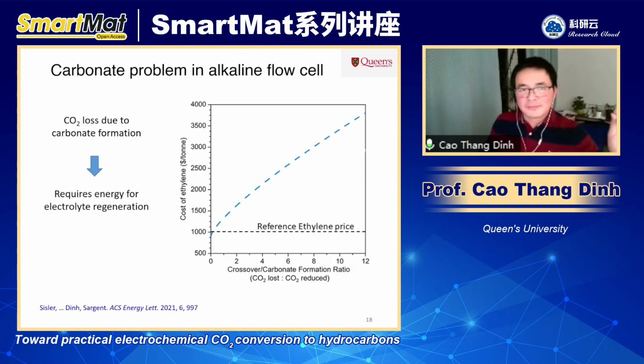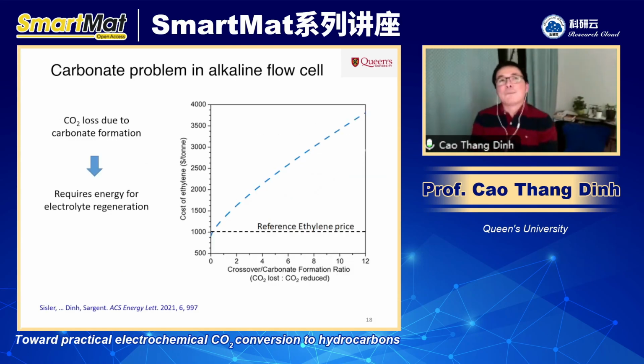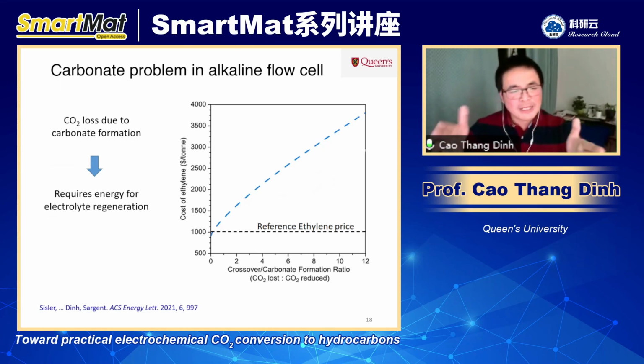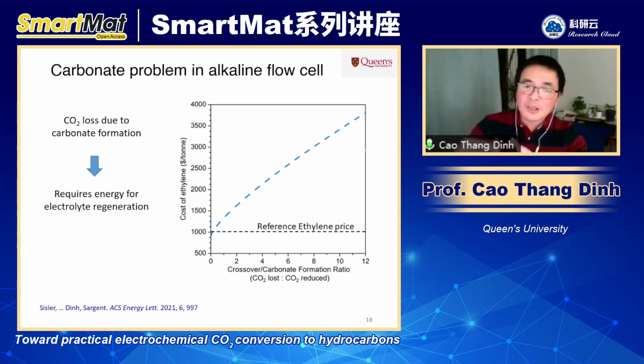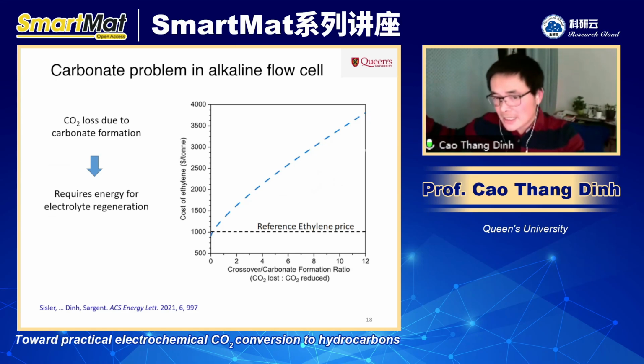So what's the problem? Well, the problem comes from the electrolyte that we use. I showed you two examples, and in both of them we use the alkaline catholyte for CO2 conversion. With alkali, we suppress the hydrogen evolution and can reduce the cell voltage, but we pay a lot of penalty for the carbonate formation. The CO2 is not only converted to ethylene, but also to carbonate and bicarbonate, so you need to regenerate your electrolytes, and that costs a lot of energy.